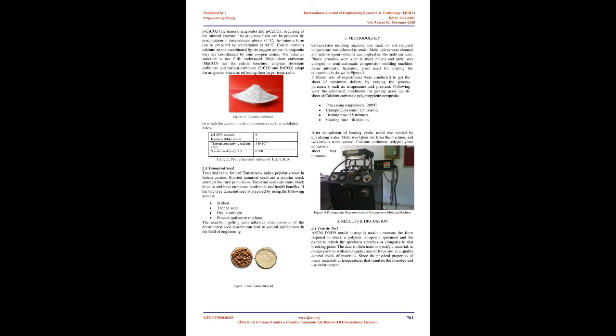Different sets of experiments were conducted to get a sheet with minimum defects by varying process parameters such as temperature and pressure. Following were the optimized conditions for getting a good quality sheet of calcium carbonate polypropylene composite. Processing temperature, 200 degrees C. Clamping pressure, 1.5 tons per square meter. Heating time, 15 minutes.